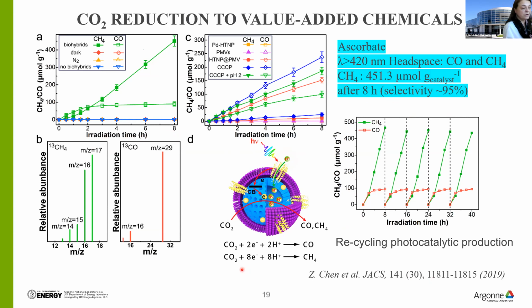So we can conclude here that, as I mentioned at the beginning, to complete CH4 methane photocatalysis, we need a lot of protons and electrons. So that's why probably we can propose that dynamics of product formation like that. First, we had fewer electrons and protons, and we observed CO formation, while after a certain time, we had enough protons and electrons inside of the hollow structure, with water inside. We observed mostly methane formation.